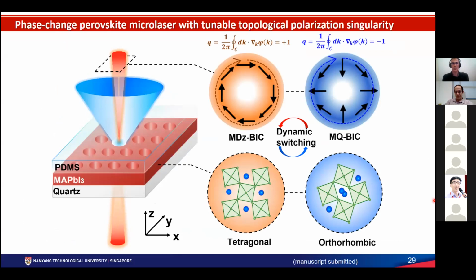So the idea was just to use something that is solution processed, so we can do nano-imprint lithography for the structuring. If you use a crystal, maybe you need to use another structuring technique, maybe electron beam lithography and so on, but this is just solution processed to start. But if you use 2D, it's also very interesting. Actually, you might have effects that are not present in the 3D one, and you could go even thinner. It depends also on the refractive index. So you cannot go too thin and have the same design, because then you will not support the structure, but you might think of encapsulating in other designs.